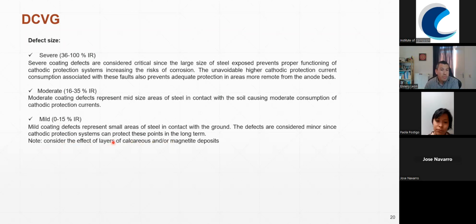It's not like that. It's also important to mention that we need to consider if around this pipeline we could have development of calcareous layers because of the CP. Remember that if we have the high pH and we have the chemical composition required for this, the CP will tend to develop a calcareous layer in the exposed steel. And then we will see that as a defect that is smaller than expected, because we will see a high IR percentage, but in reality, once we excavate, it's going to be